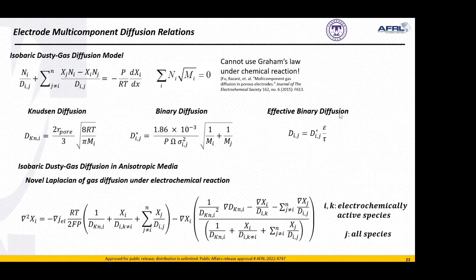Now, moving on, we think about the gas transfer that happens within the electrode. The most accurate diffusion model for multi-component gas diffusion is the dusty gas diffusion model, where the solid phase is also considered to be essentially a gas species. And you have what's called Knudsen diffusion, which is defined by the average mean free path of a particle at a certain temperature. And it will also be a function of the local pore size as well. So this becomes relevant, especially for hydrogen on the anode.